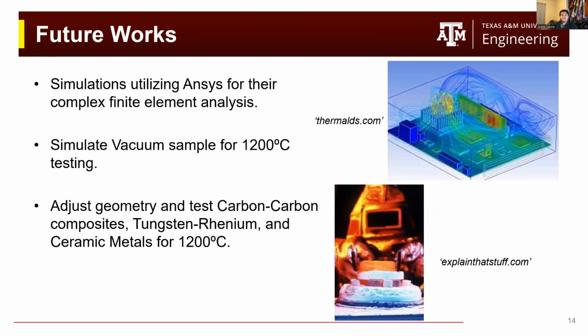ANSYS in particular has a complex finite element analysis that can better simulate the thermal properties of the grips at 1200 degrees Celsius. As you can see here, it shows the flow of heat, which I have yet to see in any Fusion 360 thermal simulation. More research can also be done into materials such as carbon-carbon composites, tungsten rhenium, and cermets, which could be looked into for the higher end temperature tests.